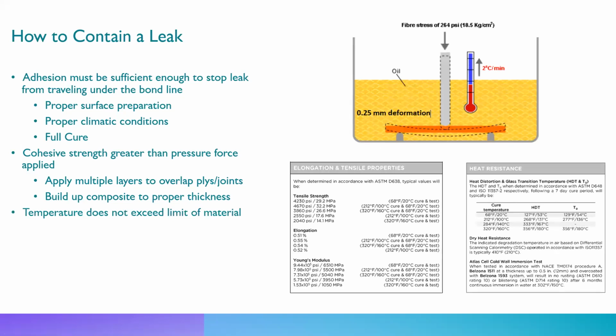Also, for long-term success, you're going to want to make sure that the temperature is within the limit of whatever system you're using. So if you have a leak on a pipe that operates at 300, you want to make sure that that product can handle 300 degrees F. You want to make sure that if it does get exposed to 300 degrees F, you know what's going to happen to the strength. As you can see, for our high temperature products, we test the tensile strength at 300 degrees. We test the Young's modulus at 300 degrees. We do adhesion testing at 300 degrees. We have to see what kind of degradation of our properties we are going to get at those elevated temperatures.